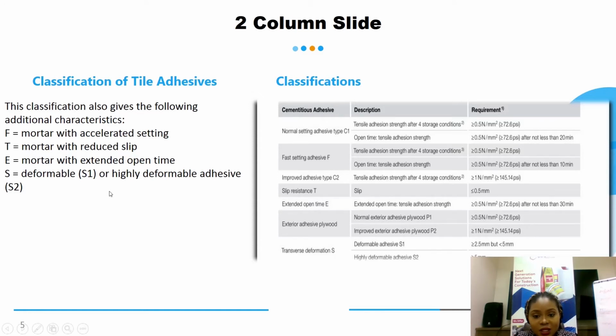So for the normal setting adhesive, that's type C, we have greater than or equal to 0.5 Newton per millimeter square, and this tensile strength is achieved not less than 20 minutes after the tiles have been placed. Then for your fast setting adhesive, that's F, we're experiencing greater than or equal to 0.5 Newton per millimeter square after not less than 10 minutes, because it's fast setting, and it's also C1. The difference is this achieves its tensile strength earlier than the normal setting adhesive.